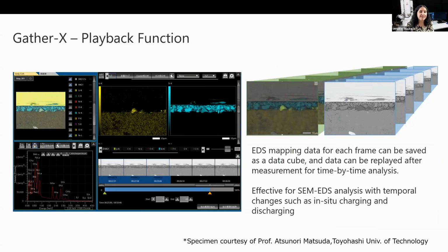Now, using our Gather-X EDS detector, X-ray maps were collected during the charging and the discharging. I wanted to mention first that JEOL's EDS software on any of our SEMs not only collects EDS maps, but also an image with each frame. So we have what's called playback analysis function to view the full time domain of our experiment. The data can be replayed after measurement, and also data can be extracted from any portion of the time domain. So this is very effective for observation of systems with temporal changes, such as this study.